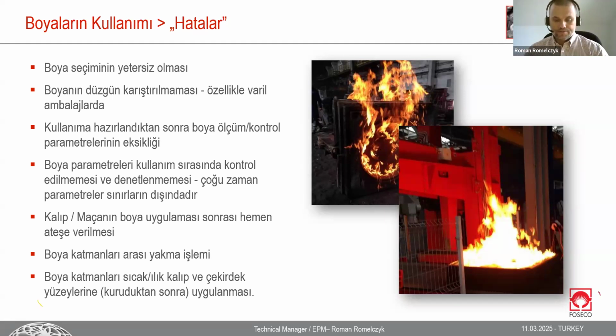What's more, this is not without reason. These pictures are put here to show the mold or core just after the coating is applied. Now we talk about alcohol-based coatings. Just after application, the mold or core is set on fire. So it means we don't wait any minutes, 10 minutes, half an hour, but immediately we burn it out. It's quite a big mistake, and I will try to say and show why.